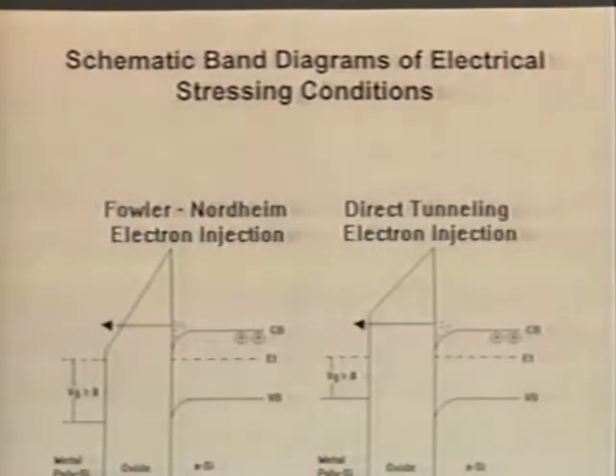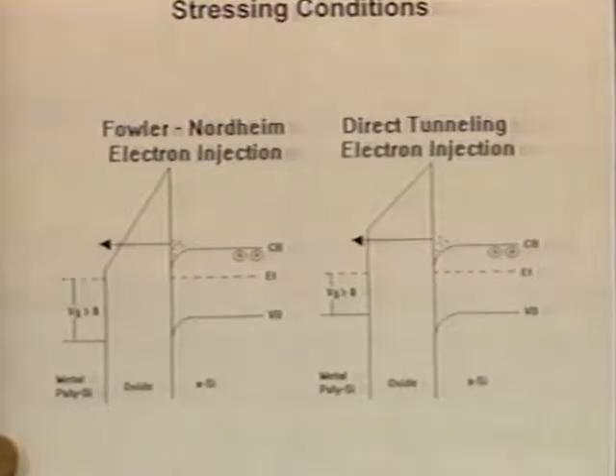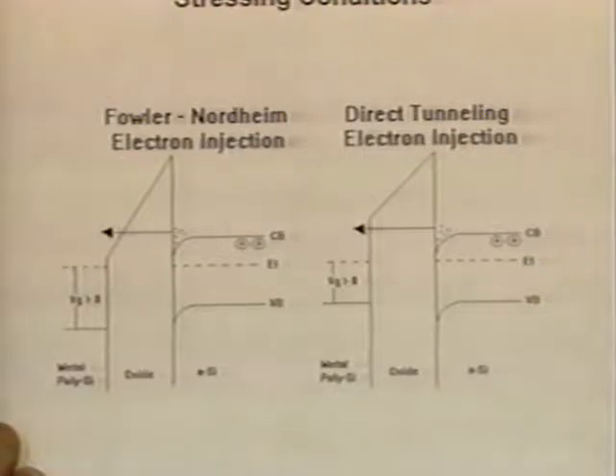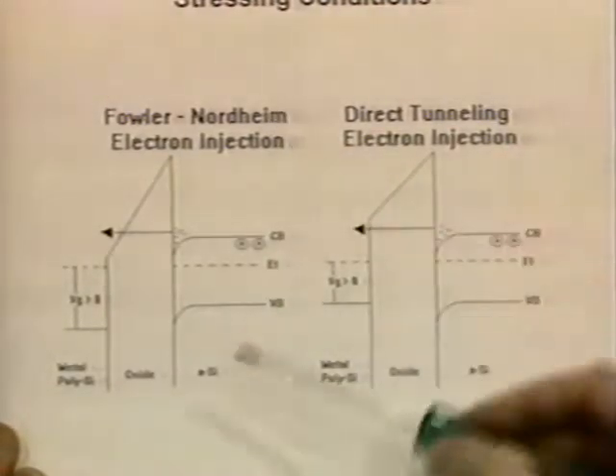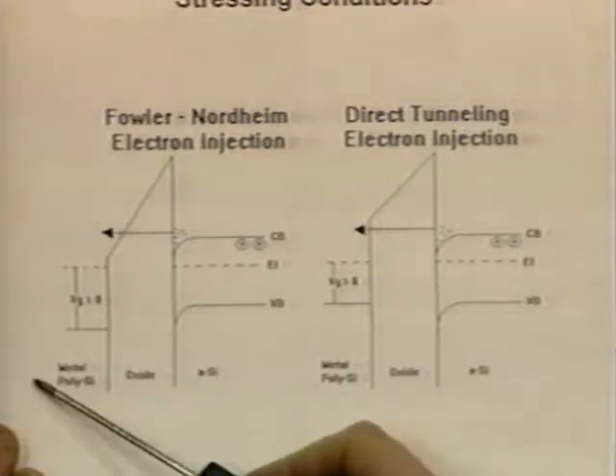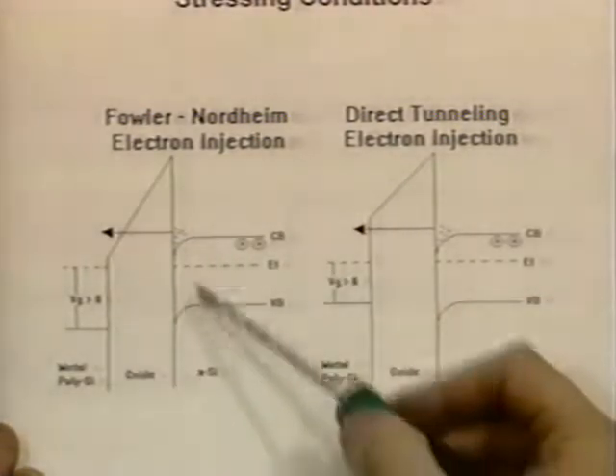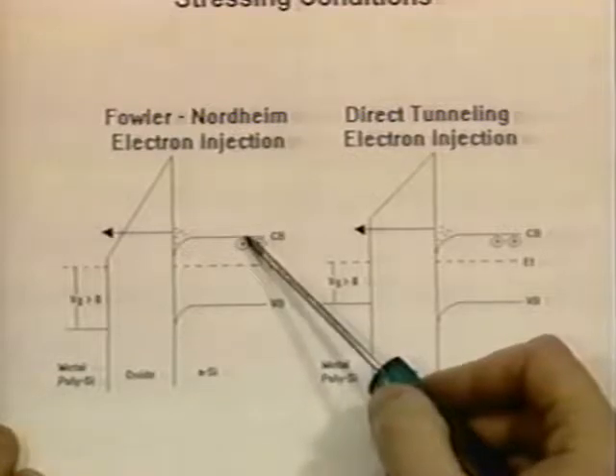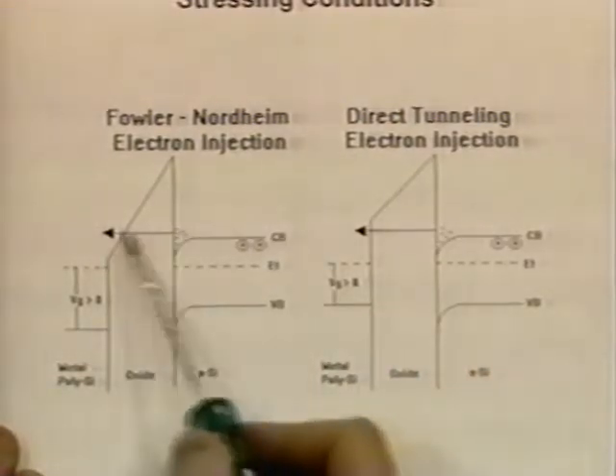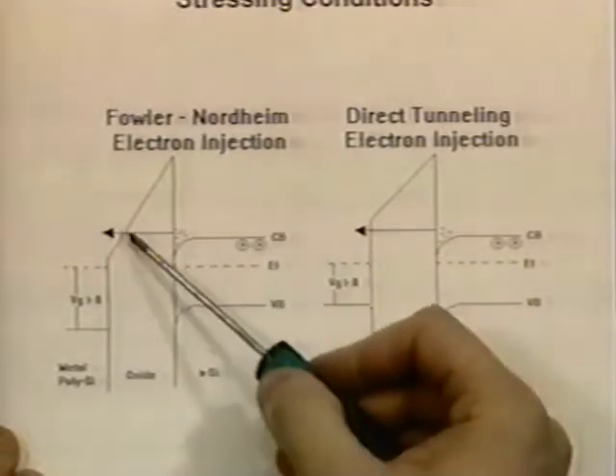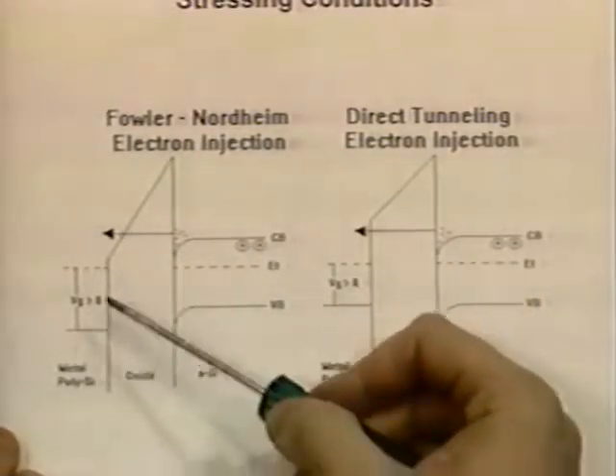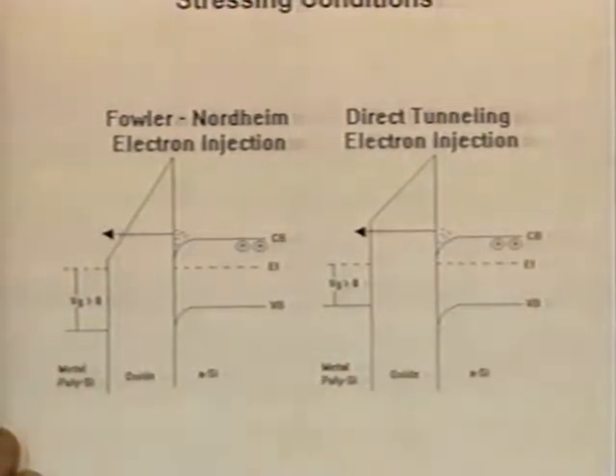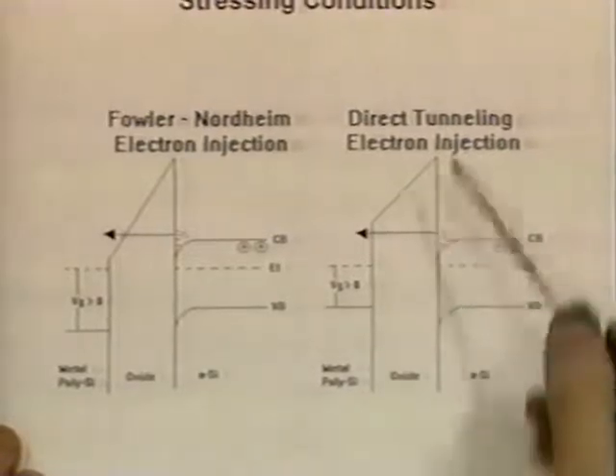I want to give you a schematic band diagram then of the electrical stressing conditions for both Fowler-Nordheim, which most people who've dealt with thicker oxides are familiar with, and direct tunneling, which is what I'll be talking about. In the Fowler-Nordheim case, again for substrate injection from the N-type silicon over towards the gate, this isn't exactly drawn to scale, but the conduction band of the silicon is where the electrons come from, and they're injected into the conduction band of the oxide. They're then accelerated, if there's any field for them left to be accelerated, and eventually are thermalized in the gate material.